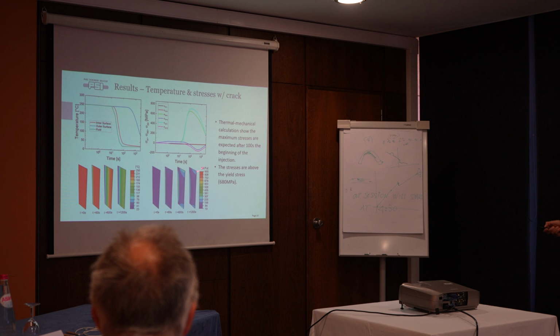We observe that they are above the yield stress, and this is because we are considering only linear elastic properties of the material, which is a rather fair assumption in this case, because we are dealing with a hardening material due to the neutron irradiation, hardened materials. And the maximum stress is expected around 100 seconds after the injection of the water.